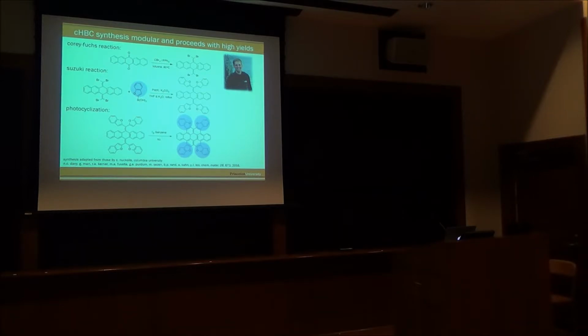Now we've also chosen this chemistry because this molecule is non-flat. It's contorted. And you'll see why this contortion matters in a little bit. Suffice to say that basically when we form films, these films have no long-range order, they're disordered. And this disorder is good because it doesn't have any pinholes and we can make nice films uniformly over large areas. And I'll come back to this in a little bit.